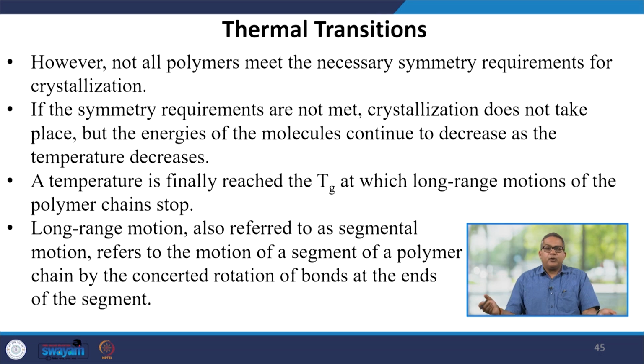However, not all polymers meet the necessary symmetry requirements for crystallization. If the symmetry requirements are not met, crystallization does not take place, but the energies of the molecules continue to decrease as the temperature decreases. A temperature is finally reached, the glass transition temperature, at which the long range motion of the polymer chain ceases. The long range motion is also referred to as segmental motion. This refers to the motion of a segment of the polymer chain by concerted rotation of bonds at the ends of the segment.